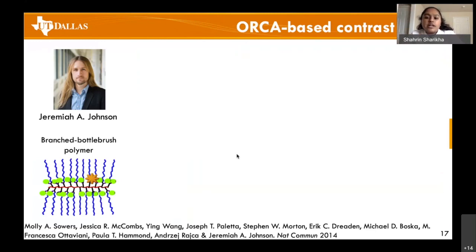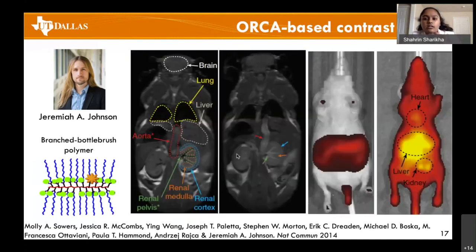But his group decided to use that to their advantage and instead create, once again, a multifunctional agent that serves in both fluorescence and magnetic resonance imaging. Nitroxide radicals only have one radical, which makes them poor in terms of their paramagnetic activity. So what they did is they conjugated a bunch of them to this polymer. Studies have shown that nitroxide fluorophores have been developed, where once the nitroxide is reduced, it helps to enhance the fluorescence aspect of the agent.